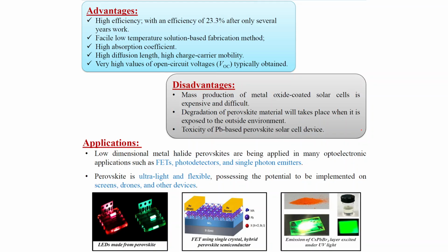So these are the advantages and disadvantages. Advantages involve high efficiency of perovskite, which is an efficiency of 23.3%. Then feasible low-temperature solution-based fabrication techniques, then high absorption coefficient, high diffusion length, and high charge carrier mobility, and a very high value of open circuit voltage. Okay. And disadvantages involve that mass production of metal oxide coated solar cells is expensive and difficult.